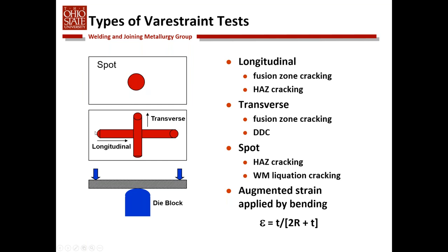There's a spot varistraint test. There's a longitudinal varistraint test, which was the original design of Savage and Lundeen. And then if you weld in the other direction, transverse to the bending load, this is called the transverse varistraint test. The advantage of the transverse test is that it isolates cracking in the fusion zone, and you can also induce ductility dip cracking. The spot varistraint test is used almost exclusively to look at heat affected zone cracking, that is cracking that occurs around this spot weld in the base metal heat affected zone.